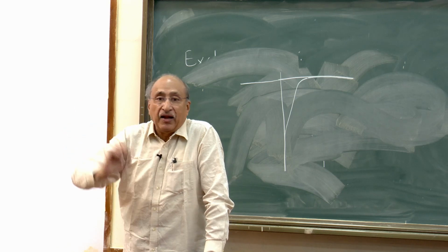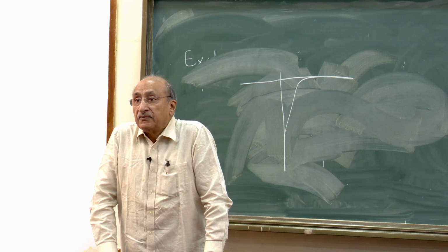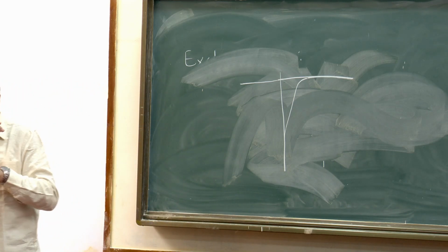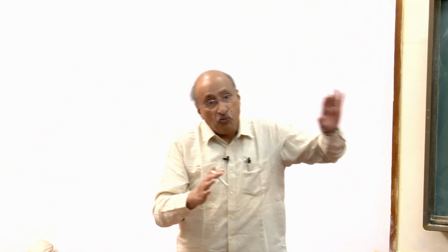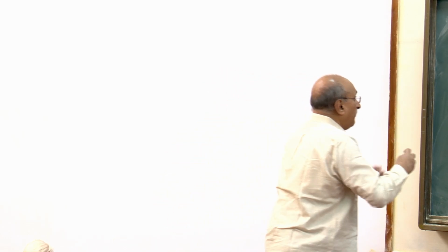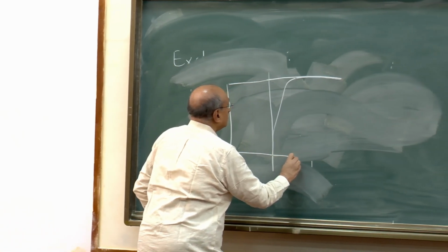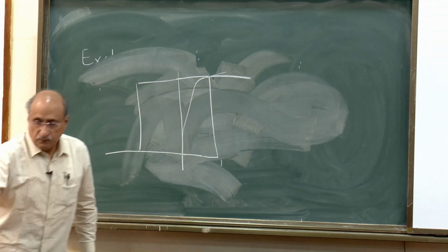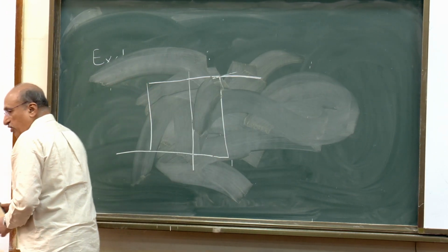It's like a potential well. They have to always move through a hard direction. Unless you are supplying them enough energy so that they can cross over that particular hard axis energy required, they will not move. They will remain in the same direction. And once you have provided it, they'll flip over and go to the other direction. This is what is called a square loop.